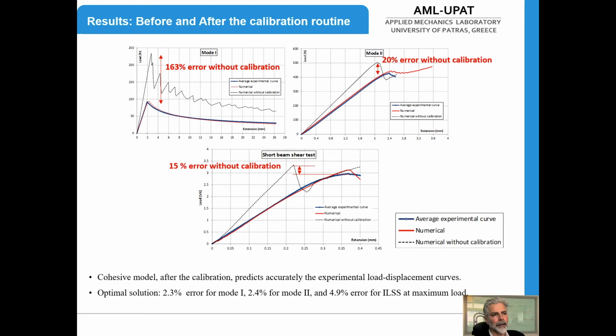Now let's see how to use the optimized calibrated material model parameters, both the orthotropic material behavior and the cohesive zone model that we have allocated to this material. Let's see what the numerical simulation of the mode 1 experiment shows, what the mode 2 simulation experiments show, and what the interlaminar shear strength experiments show. Let's go to the top left diagram over here. The solid black line is the experimental results. The red line is the simulation of the mode 1 experiment in case we have used the optimized material parameters. Finally, the dotted line curve is the simulated mode 1 experiment in case the reference material parameters have been used, not the optimized ones.